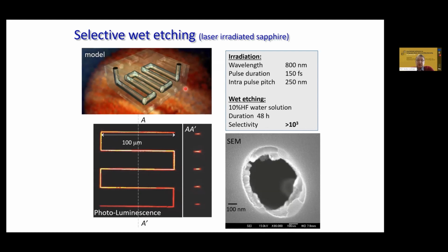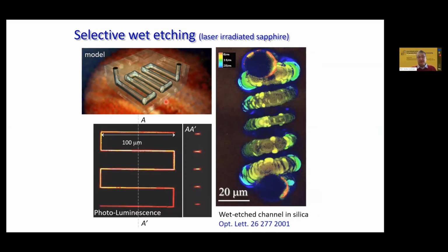Okay, so next we always asked about applications. So one application could be that we use modification of hard materials, glasses and crystals. In this case, for example, sapphire. You pattern by single shots some microfluidic channel inside the subsurface region of sapphire, and then you can etch it out in acidic solution, then fill with the dye for inspection. So you see the formation of 3D structures inside.